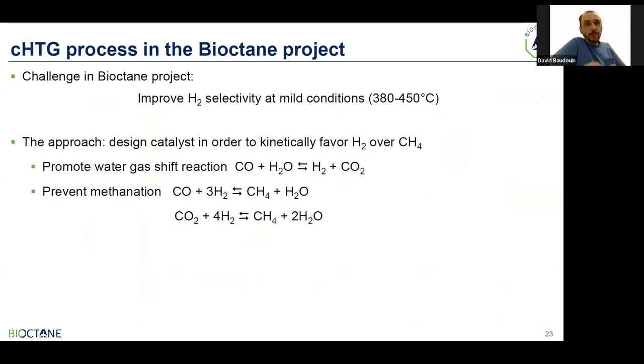So, of course, in the BIOCTANE project, I mentioned that our aim is to produce hydrogen selectively. And if you followed properly, you have seen that at lower temperature, methane is favored. So that's the challenge that we have in the project. Methane will be thermodynamically favored. Now, kinetically, we can still favor hydrogen over methane. And there, of course, we have to promote some reactions versus others, so kinetically favor these before methane actually has time to form. And this is the whole point of the project in catalyst design, so that we can favor some reactions and disfavor others.